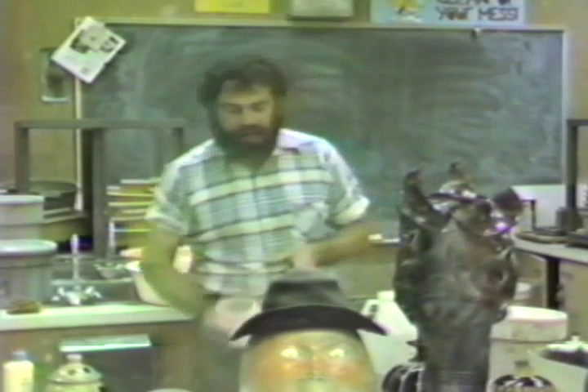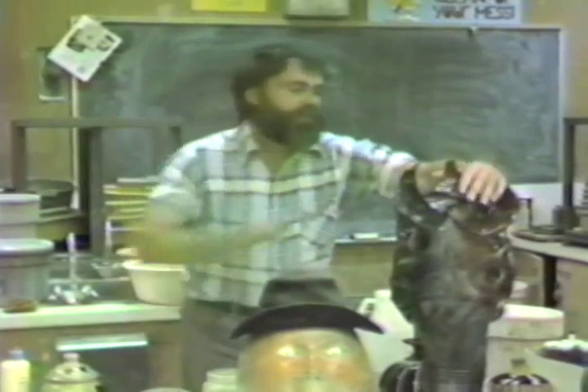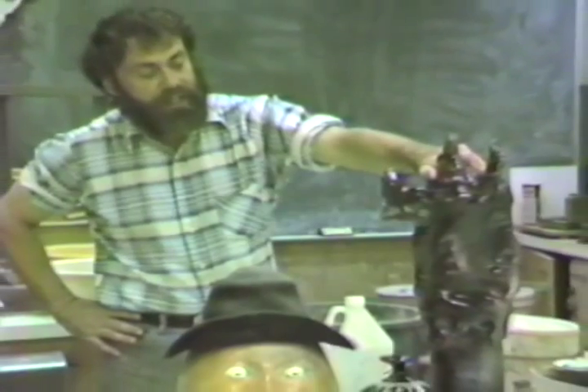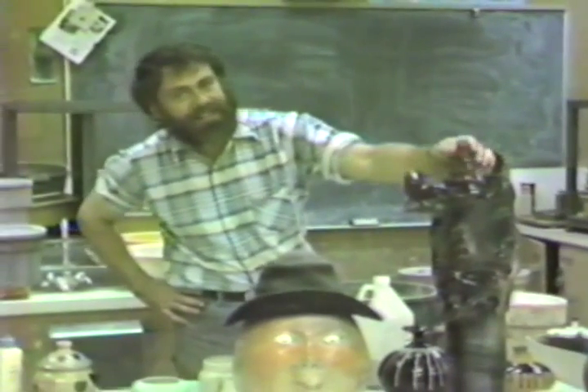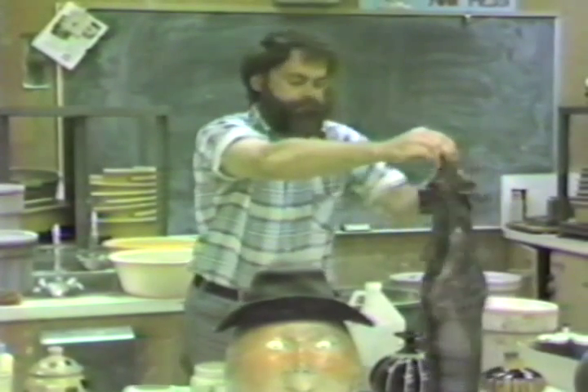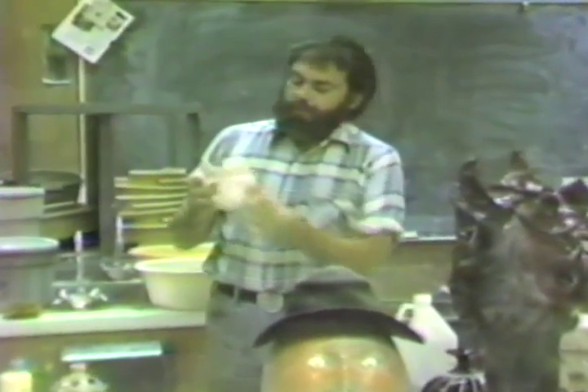But say, for instance, if I had an appendage, and I do have one on this piece right here, like this spot right here, if you put the glue underneath this, if it had fallen off, and then fired it, then gravity would want to pull it off the piece during the fire because the clay goes up to 2300 degrees. And it goes back to the plastic state, just like when you got it out of the bag. So it wants to sag, it wants to give. Okay, the XL is one of the products that we use here at West Valley for gluing things back together.